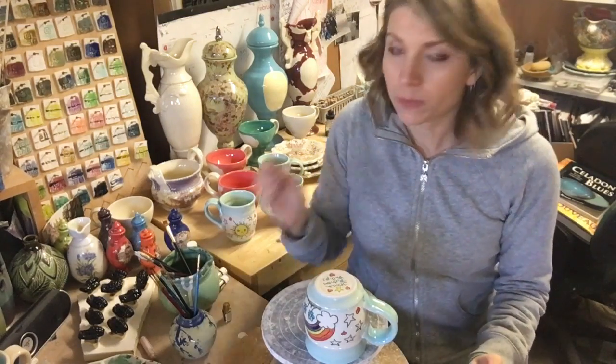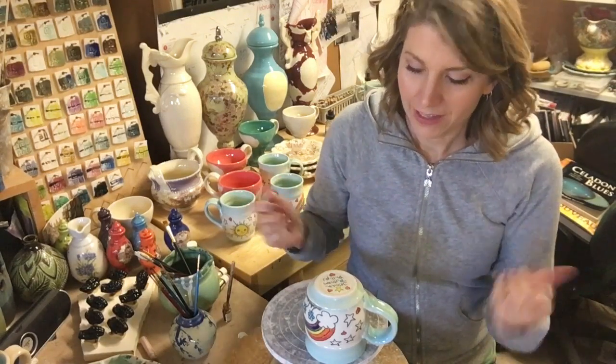It's just simple brushing it on and firing it to 017, medium speed, well-ventilated kiln, and you'll have some awesome gold pieces. The same thing applies to platinum luster, mother of pearl luster. They all go to the same temp, which for me, I fire my china paints, my commercial decals, so any vintage commercial ceramic decal that I apply, and my luster all go to 017.